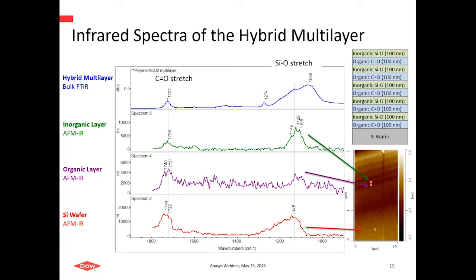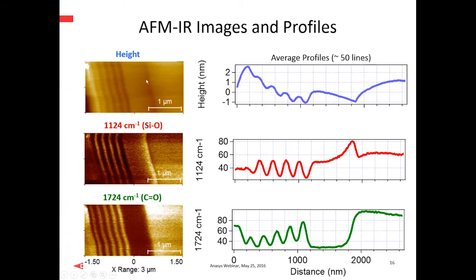We now sit on these 2 separate resonances and do some mapping as before. You can see we have the height image at the top, that due to the inorganic polymer in the middle, and that due to the organic polymer below. And if we do average profiles, we show those on the right. And so here we have a very smooth surface in this case from the FIB polishing. It's only a few nanometers of texture. But clearly we can make out all 5 layers of each polymer in these average profiles. We can clearly see them.